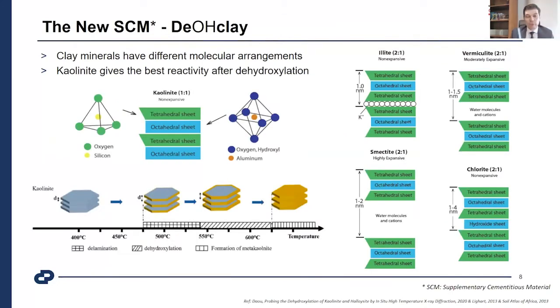What is the concept of thermally activated calcined clays? It's just clays, a very well-known and abundant material all over the world, with some specific mineralogical compositions available. The best known are the 1-to-1 and 2-to-1 compositions, but when we look at reactivity after thermal processing, the most reactive one is kaolinite, and after that illite and montmorillonite are also reactive materials. But kaolinite differs from the other clay minerals due to its 1-to-1